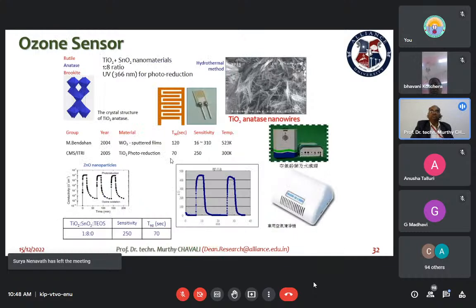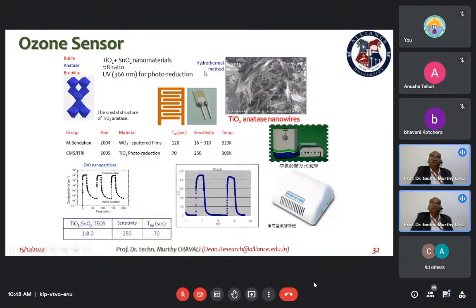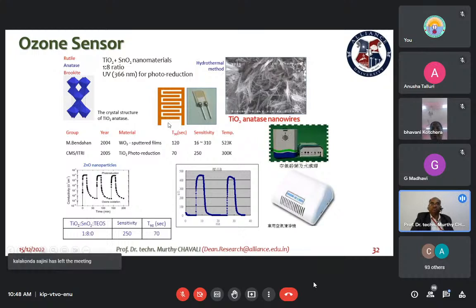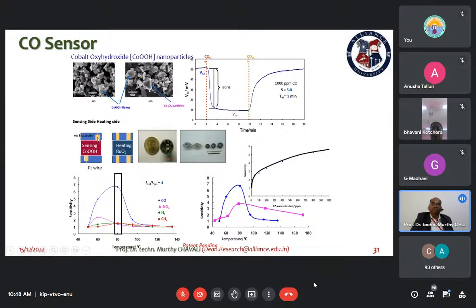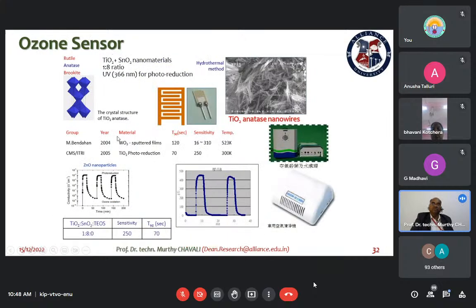And we also developed over a period of time TiO2, SnO2 nanomaterials in combination in a 1:8 ratio, so that we'll be able to generate a sensor which is specifically useful for detecting ozone. If you see this particular physical sensor, this is completely different from this type of sensor. We try to improve the surface area of this gold electrode here, so that you have a lot of contact and ultra trace levels can be detected by using this type of sensor.